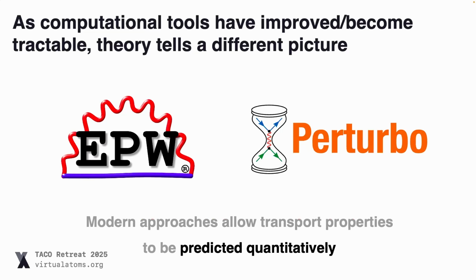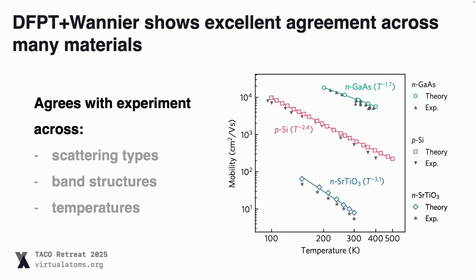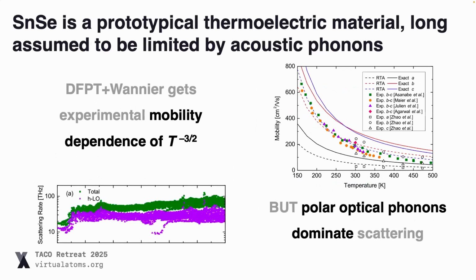And as these theoretical tools like density functional perturbation theory plus Wannier have become developed, we've now been able to get results in very nice agreement with experiments. And so we wanted to use these as a kind of fundamental insight into this behavior. So this is just to show that density functional perturbation theory plus Wannier agrees very nicely with lots of different materials across scattering types, across different band structures, and across different temperatures.